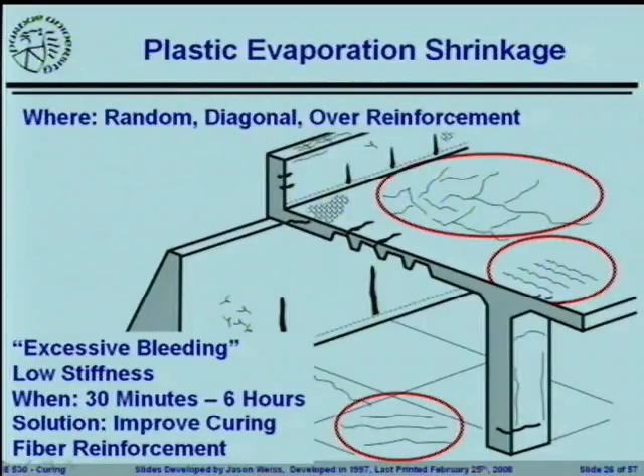The second component of this is really the component that gets the most discussion, and this is the evaporative component of it. It's going to occur over reinforcement. It's random locations on diagonals depending upon the orientation of the wind. It's going to occur very, very early on. The solution is really to either improve curing or use fibrillated polypropylene fibers or cellulose fibers, any type of fibers that has a very, very high surface area. High surface area per mixture.